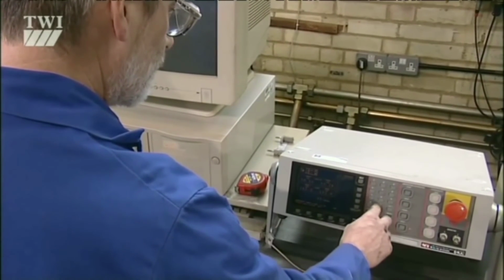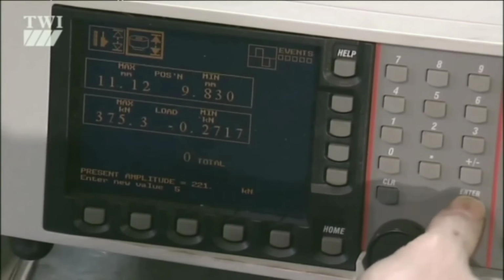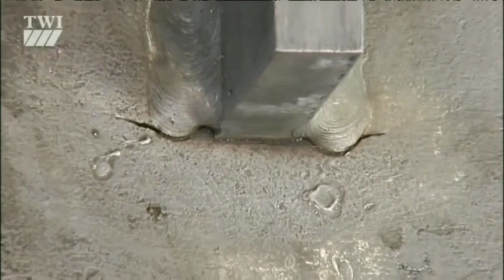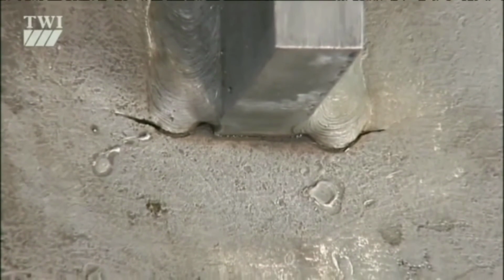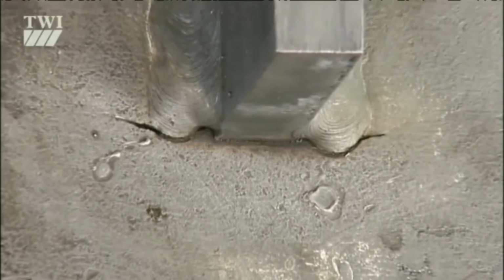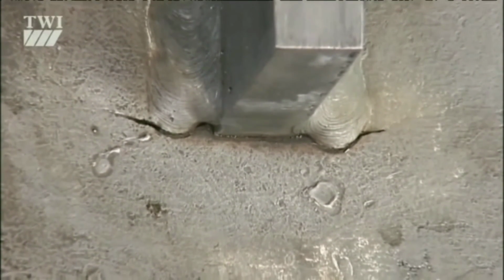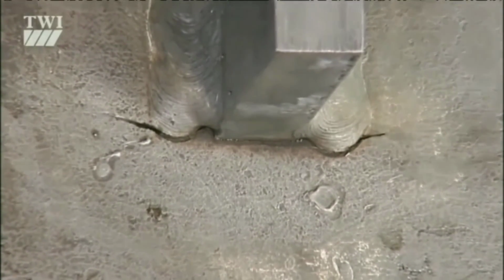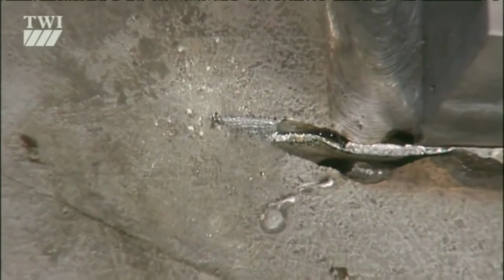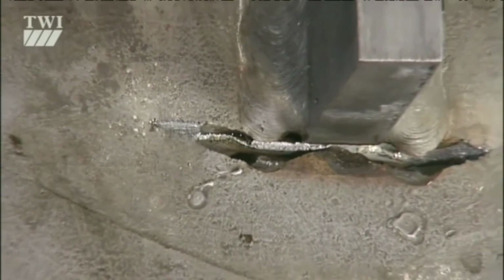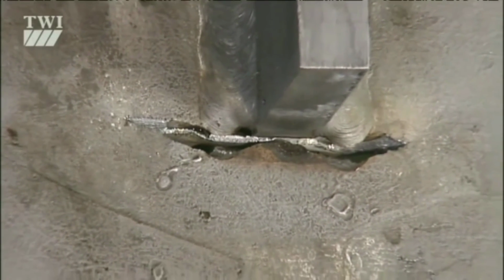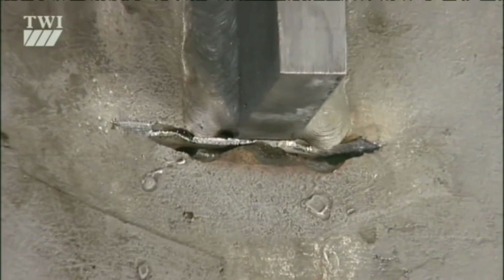Now, contrast this with a similar specimen in a fatigue test. A cyclic tensile stress is applied hydraulically. Eventually, it causes fatigue cracking, just here at the end of the weld. But the crucial thing is that this has happened at a stress well below the elastic limit. Here, fatigue cracking appears at the weld toe because of the local stress concentrations and also small weld imperfections.